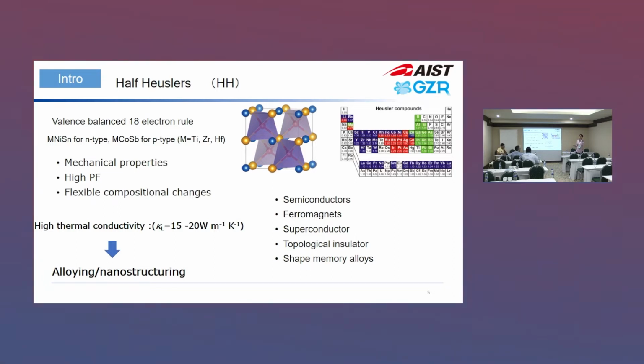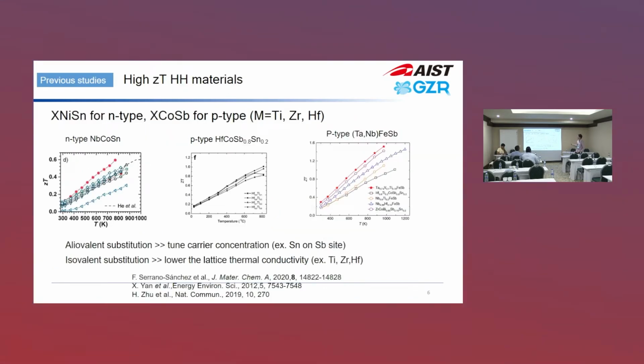We want to reduce it, so people usually use alloying or nanostructuring to reduce the thermal conductivity. These are typical high performance Half-Heusler materials, a combination of three elements, basically 1-1-1, like niobium cobalt tin or hafnium cobalt antimonide. ZT can reach around 1, which is not that high, but the mechanical property is really good, if you think about hard situations like vibrations or something like that.